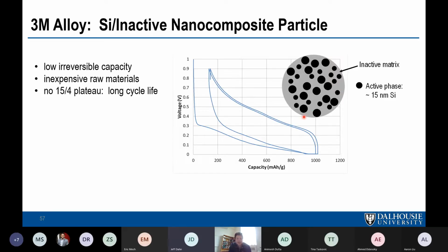But with an alloy, you don't have this SiO issue of having an irreversible consumption of lithium. And so the irreversible capacity can be small. I think the lowest they achieved was something like 15% irreversible capacity, as opposed to 50% for SiO 1-to-1 theoretically. And you can restrict the volume expansion too, because you're diluting the silicon. And you don't have any 15/4 plateau because of this stress voltage coupling in the particle.